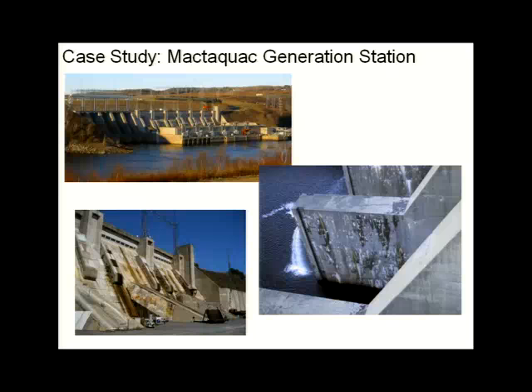I don't want to bog you down too much in boring details. We'll show you a project that I think is pretty fascinating, where fly ash is actually going to be used very effectively. This is the Mactaquac Generation Station, a hydroelectric power plant in New Brunswick, Canada, so far on the eastern coast, in the Atlantic provinces. You can even see from a fairly decent distance away the amount of cracking, the staining in the structure, and the efflorescence coming just from ASR.